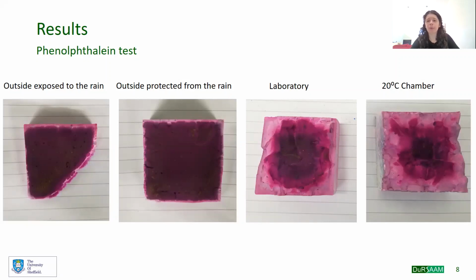So phenolphthalein is a molecule that is colorless when the pH is below 9. So the samples are all pink, which is different for Portland cement systems, which will be colorless when carbonated. But we can see here a different shade of pink. We can see a lighter shade of pink, which is due to a lower pH, but probably a pH above 9, which is in agreement with previous studies.